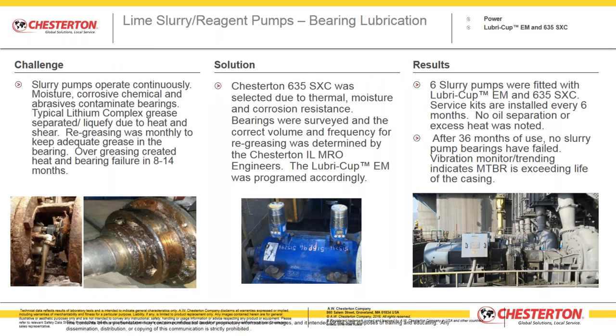And a small cost analysis for your consideration. Over-greasing: when a bearing starts to corrode, we start to hear noise. We can't stop the pump, so you begin to over-grease to help the pump get along until we can repair it. And then we suffer from excessive heat and eventually bearing failure. So one thing we can do to overcome corrosion with all this water contact is to use an anti-corrosive grease, in this case the Chesterton 635, and automatically dispense the grease via the lubricups.